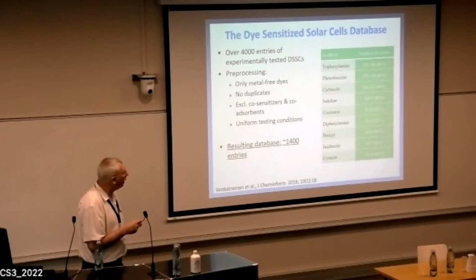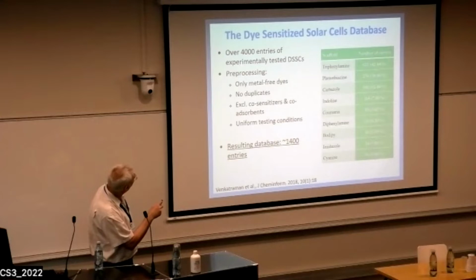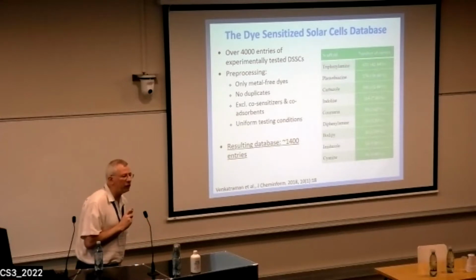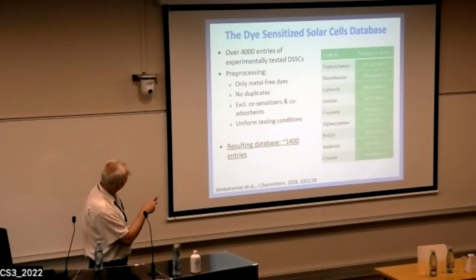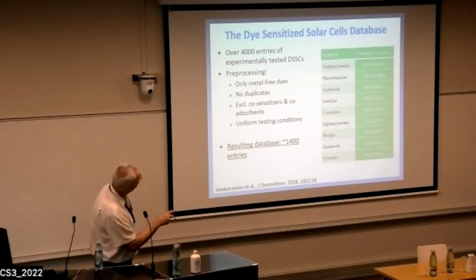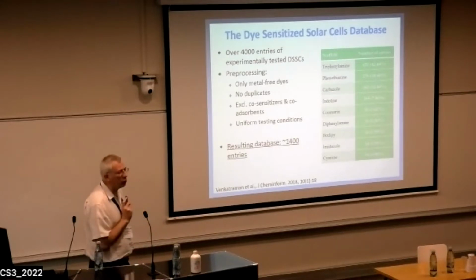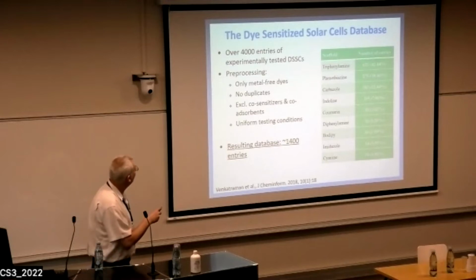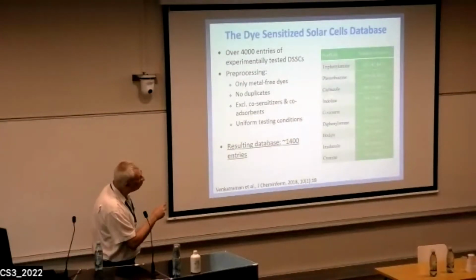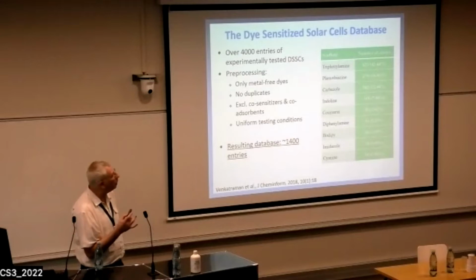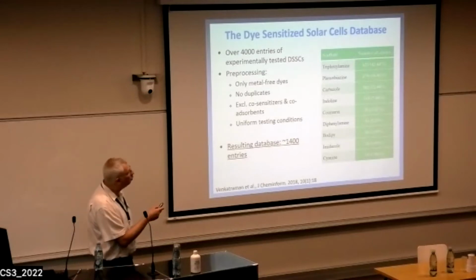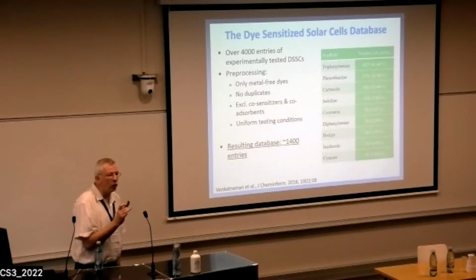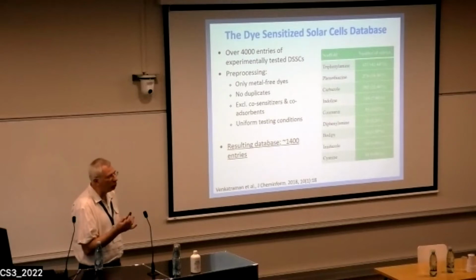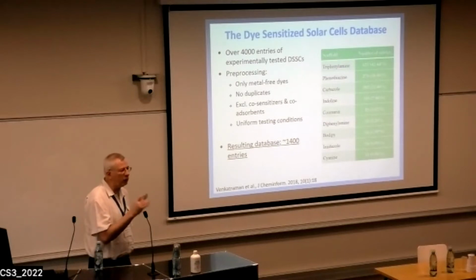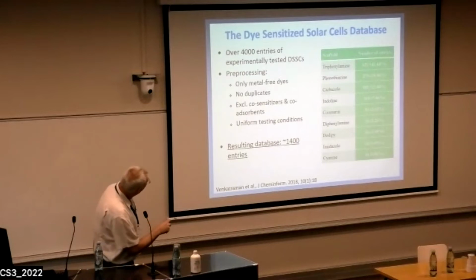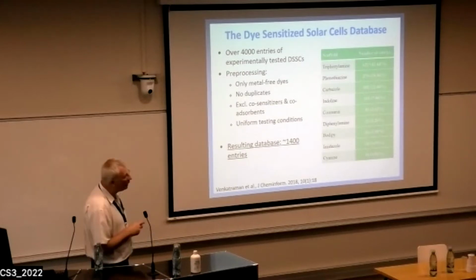So fortunately for us, a few years ago, a database of dye-sensitized solar cells was developed and published, with over 4,000 entries. These are the main functional groups or main compound groups in these cells. So we did some pre-processing to consider only metal-free dyes, no duplicates, and we made sure that the conditions which were tested are the same. So anything which was not measured under the same conditions was simply removed. We ended up with this many dyes,